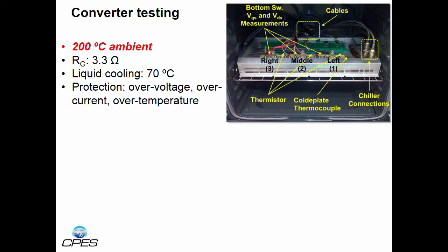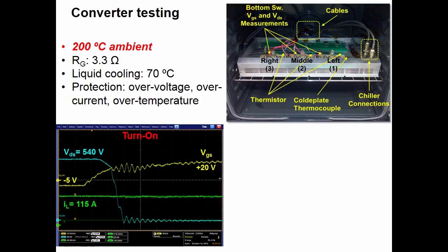This converter was put into a thermal chamber where the ambient temperature was set to 200 degrees Celsius. The module substrate temperatures were monitored using the embedded NTC thermistors, and additional thermocouples were used to sense the ambient and cold plate temperatures. The converter was immersed in this high-temperature environment for 1.5 hours while electrical tests were performed. Based on the thermistor measurements, the module substrate temperatures were at approximately 100 degrees Celsius. Double pulse tests were then performed at 540 volts and 115 amps.